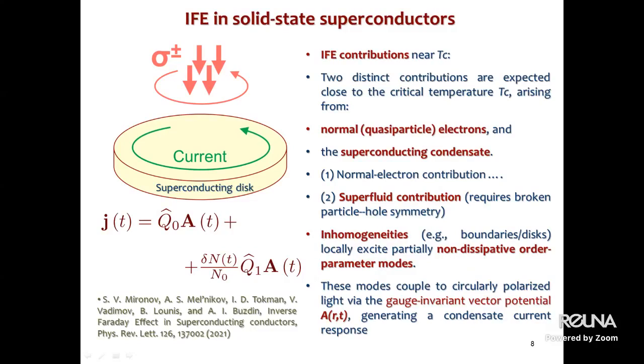The physics behind normal electron contribution we have discussed already. But the superfluid contribution requires broken particle-hole symmetry. Inhomogeneities, like boundaries or some other inhomogeneities, locally excite partially non-dissipative order parameter modes, which are in the system. And these modes couple to the circularly polarized light via the gauge invariant vector potential A, generating a condensate response. So some few words about the physics behind. It's on the next slide.